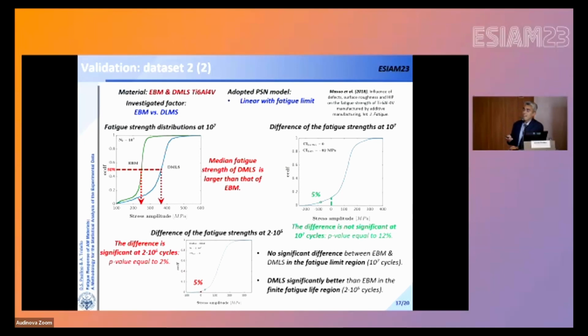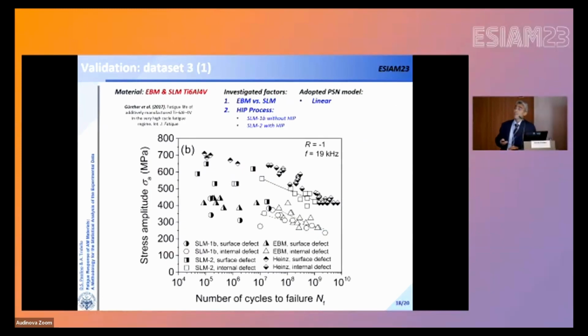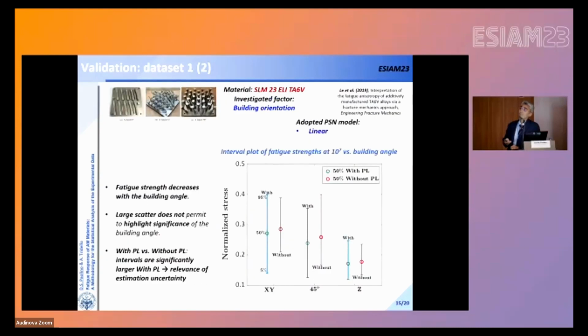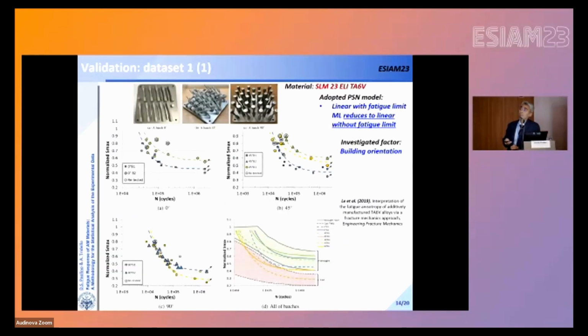Then this analysis showed that not only the fatigue scatter must be taken into account, but also the fatigue life at which the analysis is performed must be considered. So depending on the fatigue life, you may have significant differences or not. The last data set is taken from Gunther et al., published in 2017. I forgot to tell you that in all the cases we are considering titanium alloys.